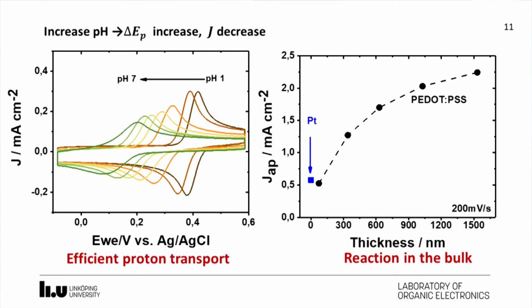Another advantage of this PEDOT:PSS electrode is that, as a polymer electrode, we found that even for a thin PEDOT:PSS film, about 100 nanometers, we get a peak current comparable to the platinum electrode. And this peak current can be further increased by simply increasing the thickness. So the reactants have access into the bulk of the polymer, and this is really good for large-scale applications.